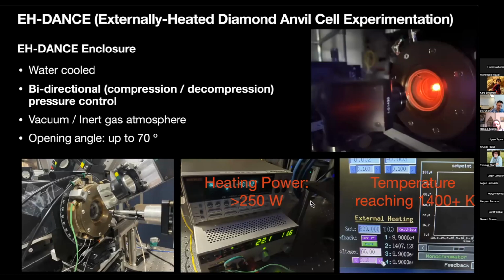And we also moved it a little bit further. We designed this EH-DANCE enclosure, which is supported by COMPRES and GSECARS. This enclosure is water cooled and has bidirectional pressure control, which is very important because if you increase the temperature, the pressure would vary during heating. It also has a vacuum or inert gas atmosphere. By placing the externally heated diamond cell in the enclosure, you can protect the diamond, and it has a large opening angle. This setup has been used in various beamlines, including 13-BM-D, which has a Brillouin scattering setup.